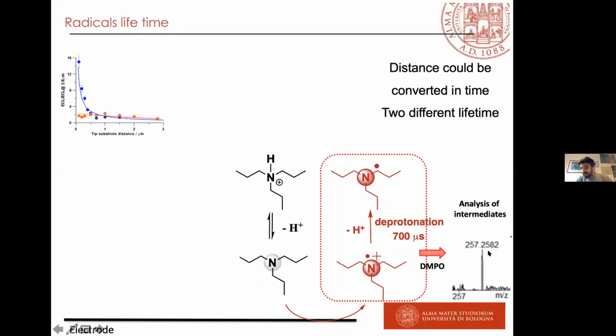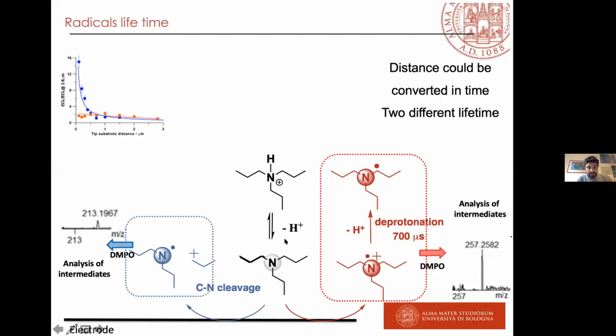Of course, we measure the radical generated from the amine, so in the alpha position, but we also observe another radical, this kind of radical coming from the CN cleavage of the amine. That's very in line with our results, because the lifetime of this radical, already measured by Bard and co-workers, is around 700 microseconds.